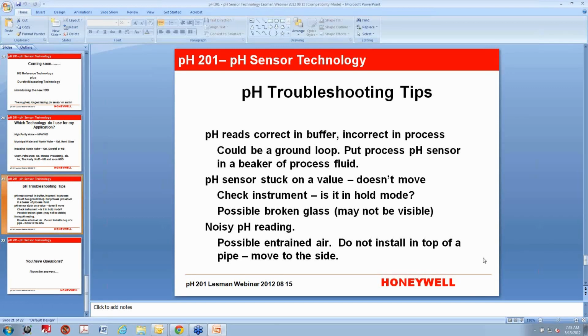Another issue I see is the pH sensor gets stuck on a value and doesn't move. And we all know that in a live process, your pH is not going to be 7.8 all the time. It's going to move a little bit. So if it's not moving, the first thing I would do, of course, is make sure that somebody hasn't put the instrument in hold, because it may be holding that value because somebody's done something with it. But more than likely, it could be broken glass.